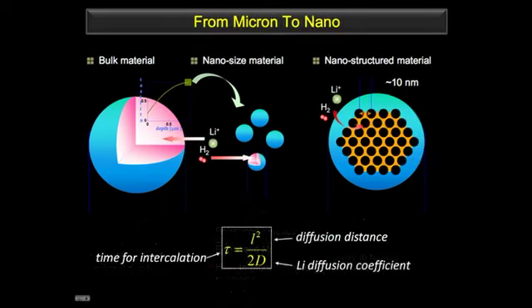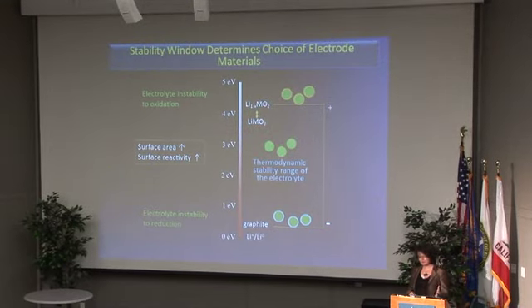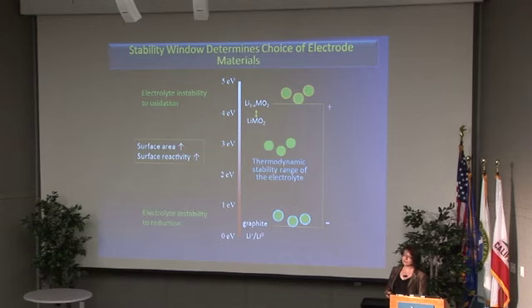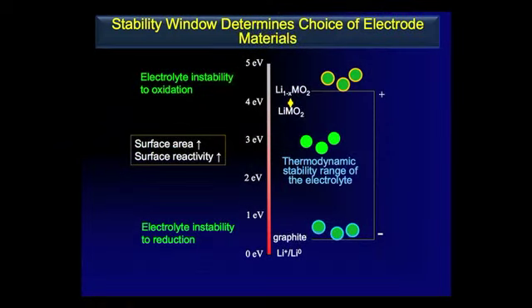So just to remind you of those limitations of mass transport, the time in any system for intercalation can be described as the square of the diffusion distance divided by the diffusion coefficient. So you either maximize the diffusion coefficient or you change your diffusion distance. Pretty simple. So the other consequence of moving to nanomaterials, nanostructured or nanoparticulate systems, is the fact that surface reactivity is always a concern in any electrode, in any battery. So at the positive side of the cell, there is electrolyte instability to oxidation, and at the negative side, there is electrolyte instability to reduction. So the smaller these particles get, the more the surface area obviously is increased, and the more destructive these side reactions at the surface can be.